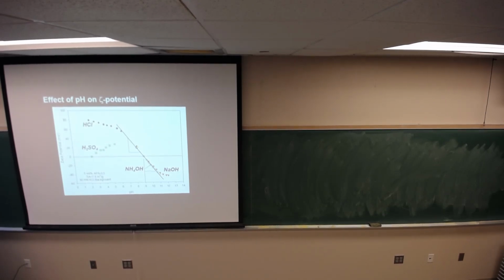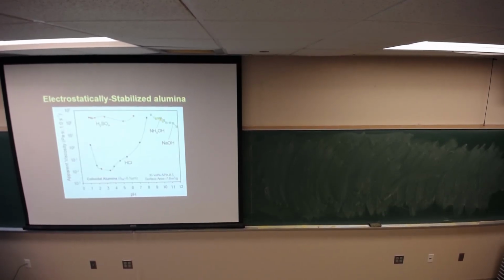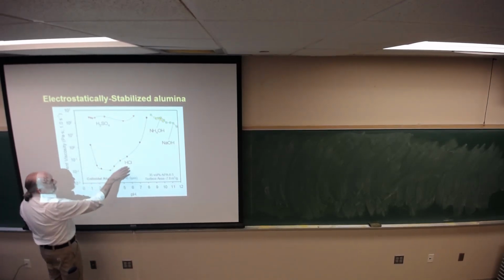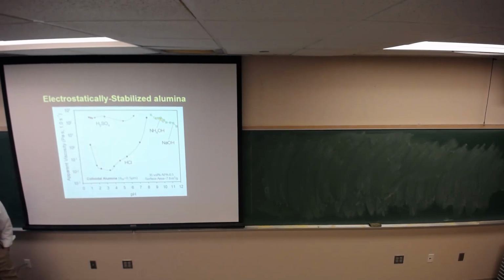Okay. So if I look now at the viscosity data, something else happens. So what you see first, here's HCl behavior, huge drop in viscosity. You can look at the math basically. If we look at the y-axis, we start about here. We're 1, 2, 3, 4, almost 5 orders of magnitude drop in viscosity with the change in pH. So it's a huge drop in viscosity. You would argue from something around sour cream to skim milk. Good? What happens on the base side?